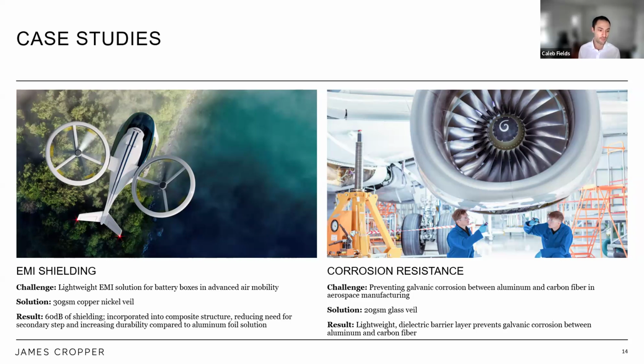So what we did is we developed a solution that's a lightweight 30 gram per meter squared carbon that's coated with copper and nickel. And we got similar EMI shielding to the aluminum foil solution, but our material reduces that secondary step because it goes directly into the composite layout. So it's a more elegant solution, and it's more durable as well because it's in the composite rather than on top of it.